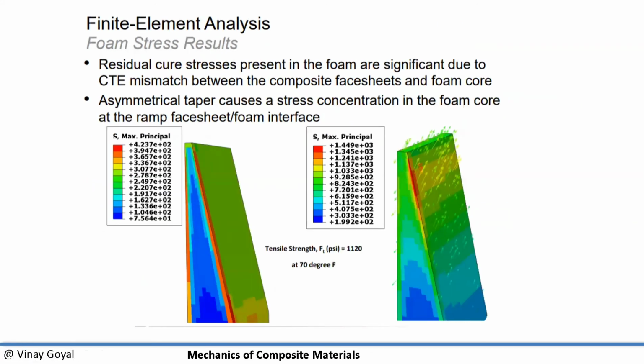If you look at the finite element analysis of this, it's actually quite eerie because you can see that we plotted the max principal stress within the foam. And you can see here the values are relatively small, 1,400. But that's important for you to note because very often we think that the only failure mode that could occur is composites, but the foam could also fail. And so there is this temptation of not doing anything about it on the foam side, but you have to really pay attention to it because in this case it's a critical failure mode.